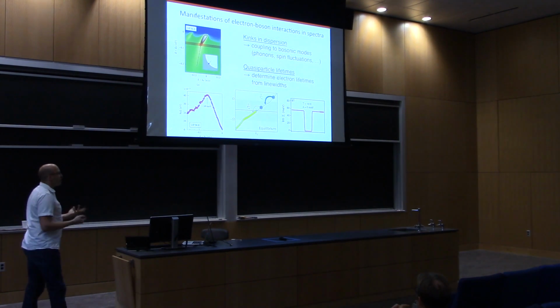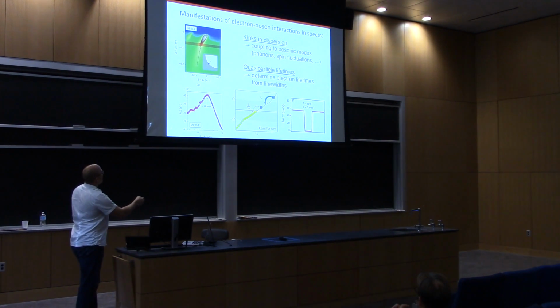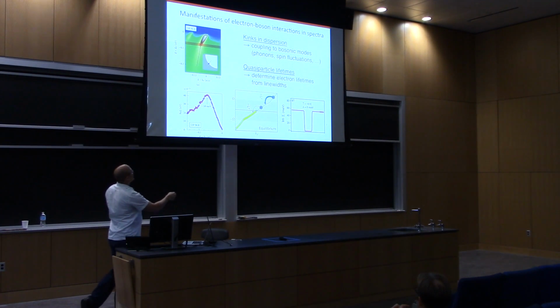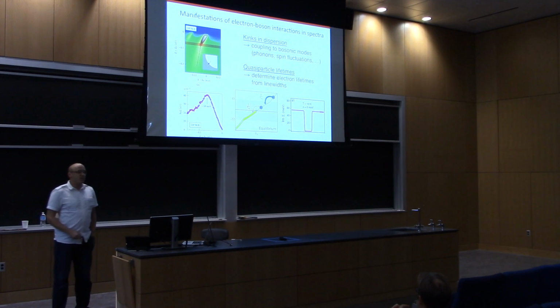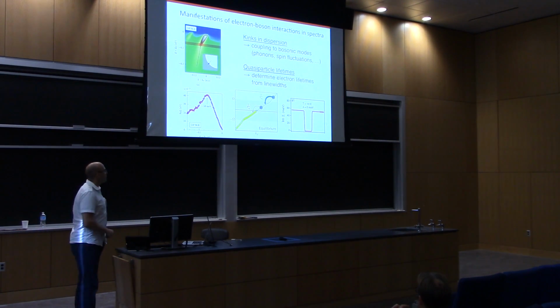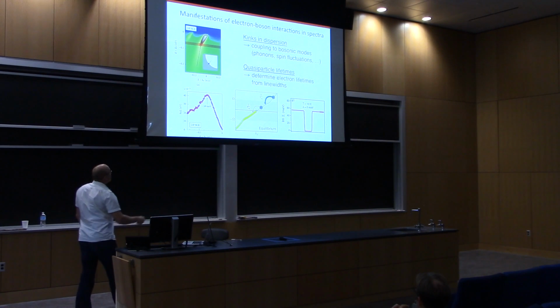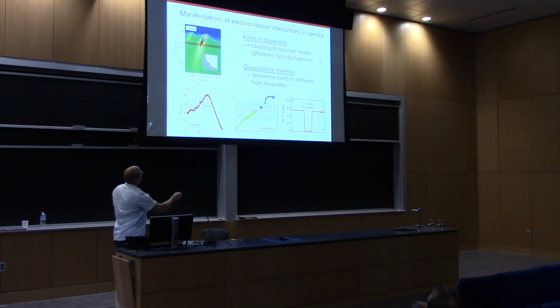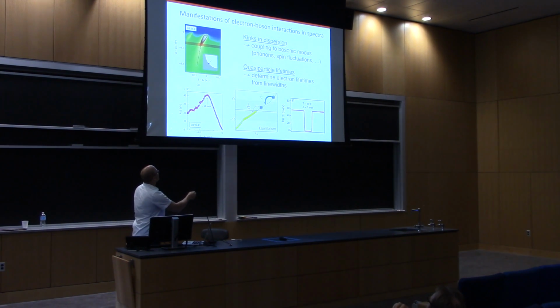What this essentially comes from is phase space restrictions. If I have a system that's in equilibrium, I've got the band, this is my band structure below the Fermi level entirely occupied, I've got my band structure above entirely empty. And if I am a singly excited quasi-particle that sits here, I can't really decay over there because I don't have any space to do so. All my states are occupied, and so I'm sort of blocked from doing this. And that's true anywhere within this phonon window, assuming I'm using this one phonon as my decay mechanism. On the other hand, if I'm above this phonon frequency, I can easily scatter down, no problem. And that's the origin of this jump up at the boson energy.